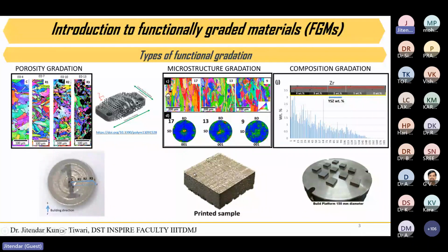At one place, if you need an equiaxed kind of grain structure, then you can adjust the parameters according to your need. And if we go to the higher energy density side, obviously you will get long columnar grains, and it will be textured. In the third case, we have printed a functionally graded yttria stabilized zirconia reinforced Inconel 718 composite. From this direction to that direction, the YSZ percentage is increasing, and that is what we have confirmed with EPMA, the electron probe microanalysis result.